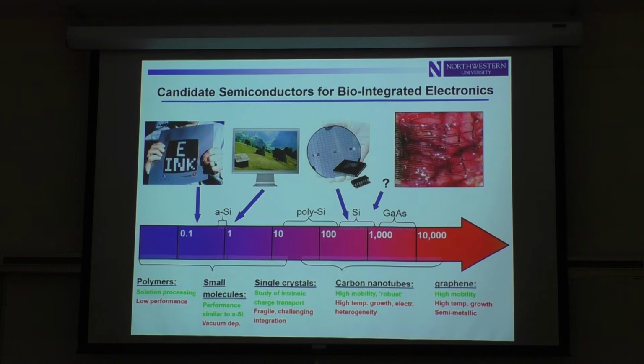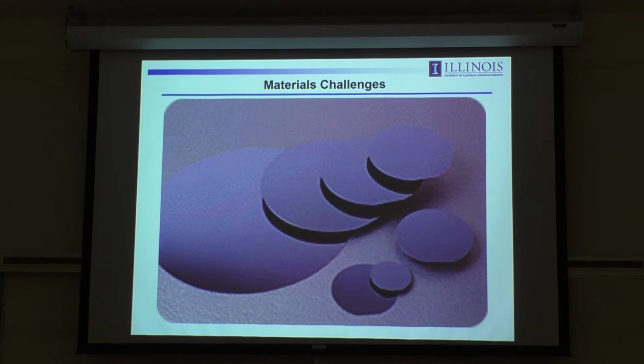But silicon at an intuitive level may seem radically inappropriate for these kinds of applications simply because the form that it conventionally exists in as a support for electronic devices is in this kind of wafer-based platform. And it's great for manufacturing of integrated circuits, very flat, and so it's compatible with the kind of optical techniques that are used for manufacturing. It's very dimensionally stable, which is good for multiple level lithography and overlay registration and so on. But from a brain interface standpoint, it has these huge disadvantages, as I mentioned to you before. And so naively, you might conclude silicon is not going to work. But it's really only accurate to say silicon in the form of a wafer won't work.